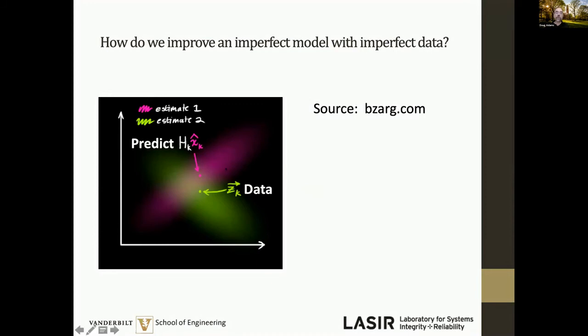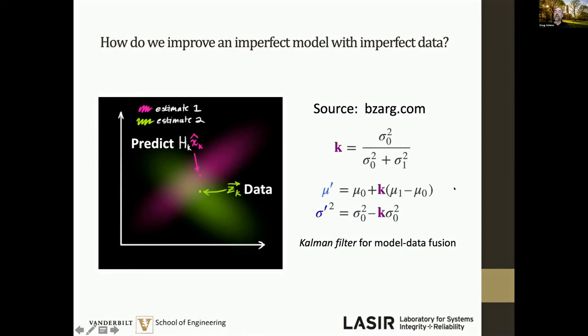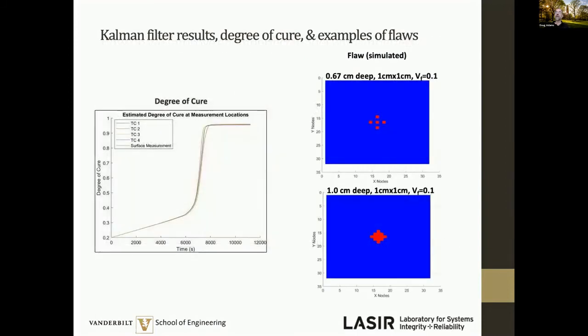And so that's what I'm showing here. You predict something, you measure something, you compare those two things, and over time, you're able to drive down the error. And what these equations show simply is that you're able to reduce both the error in the estimate, but also you're able to reduce the standard deviation. So you're increasing your certainty in what the estimate is, for instance, of the temperature beneath the surface. So we're using this Kalman filter with the data that we obtained that I showed you earlier, and these are the kind of results we can get.